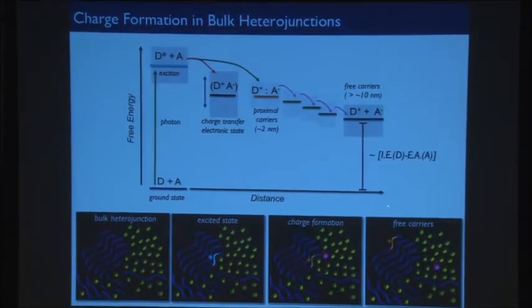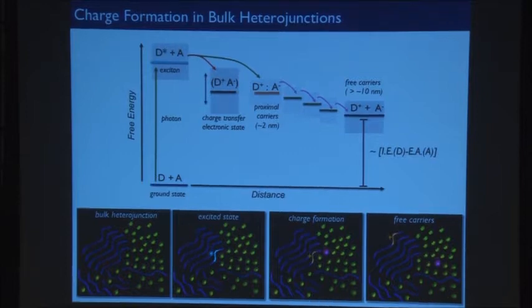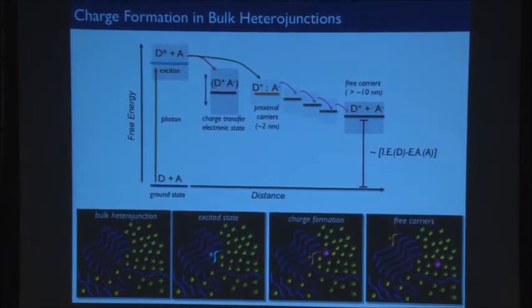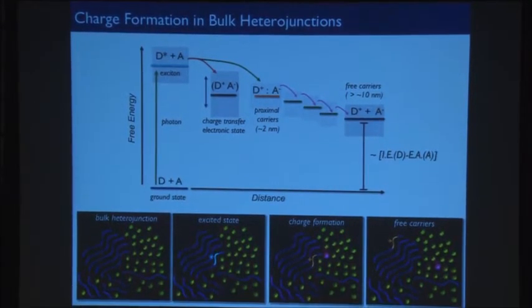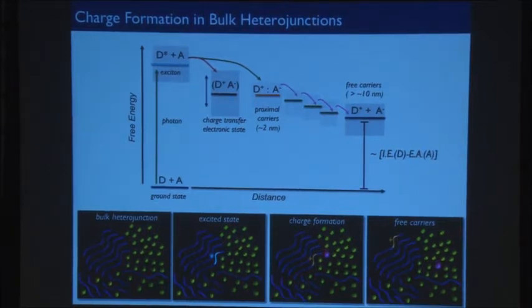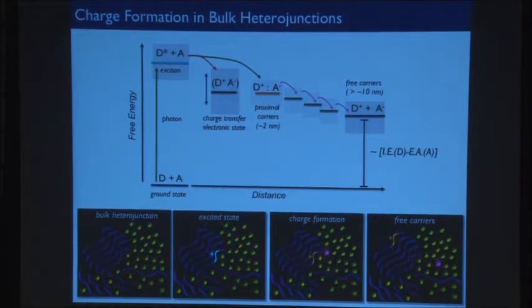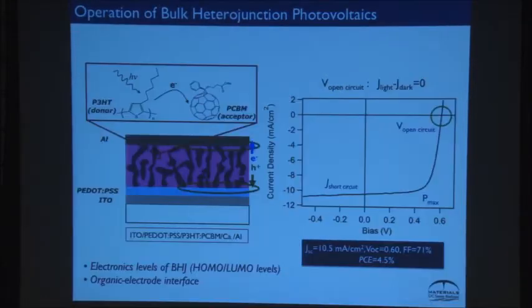And then those charge carriers will drift apart in the electric field set up by the electrodes. Okay? And then they'll go downhill in energy, basically to something that's related to the electronic levels of the donor, which is the polymer, and the acceptor, that's the fullerene. Okay? Now, when I look at that, the electronic level difference between these two materials sets this open